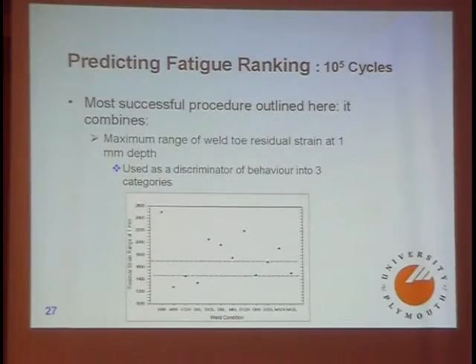So as I say, what we've looked at is a wide range of how best to describe this: changing gradient at the weld toe, range of hardness and strain at the weld toe, and gradients at the weld toe. And what I'm presenting this morning to save time is just what worked the best. So for 10 to the 5 cycles, we were fairly successful in predicting the fatigue ranking of these welds, which I think is a very positive sign, I must be honest. For 2 million cycles, we weren't so successful, for some reasons that I have insight into, I think.